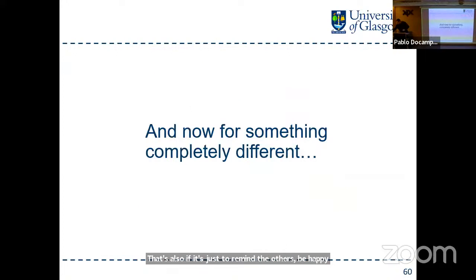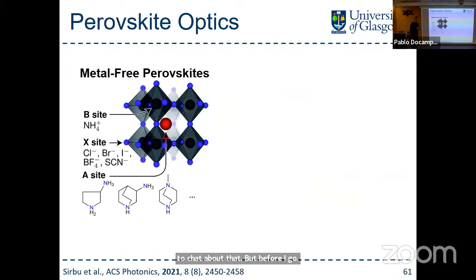But before I go, I want to show you something completely different. So I've been talking about photovoltaics for ages. Let's now take a step back. This is a very tunable structure, but you're not limited to just sticking in lead. You can put something else in there. So if you put an ammonium cation in there, you keep the same iodide, but you can put something else like these bulky organic ammonium cations. You actually get a perovskite structure, and now you don't have a metal in it. Now, I was talking about how the optoelectronic properties arise from the lead halide hybridization. These do not conduct at all. They're terrible.